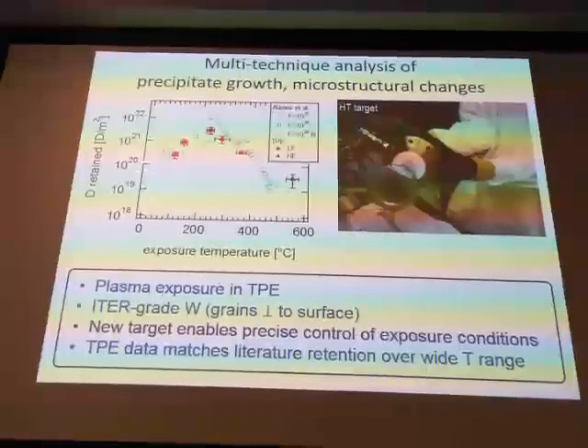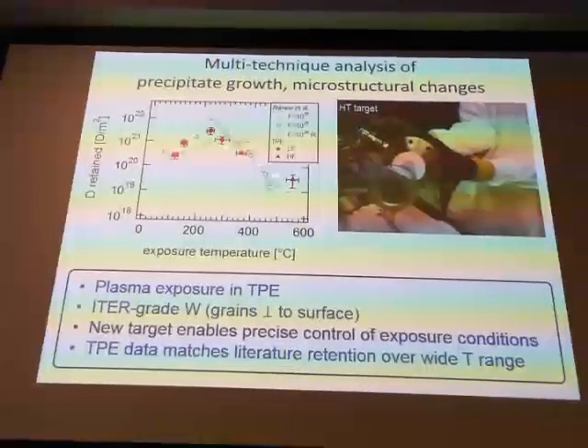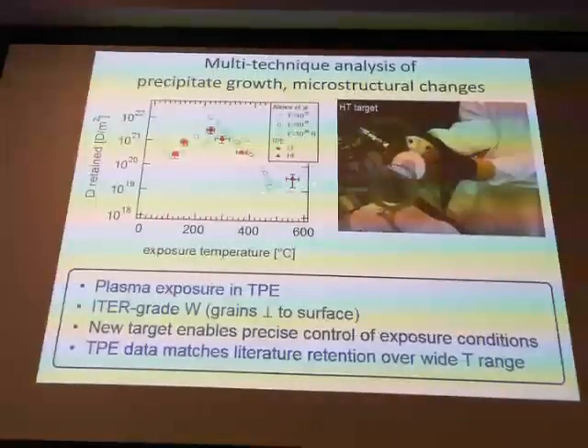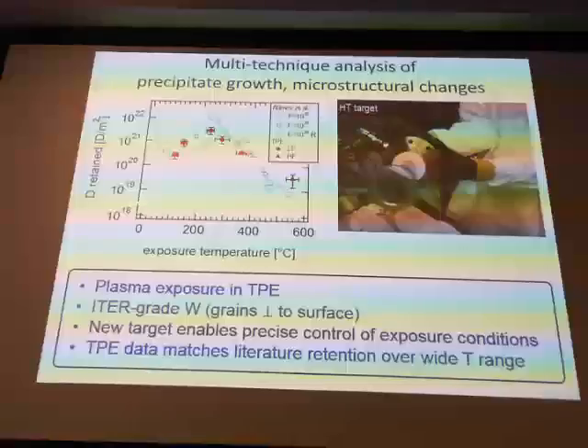This is an illustration of measurements that we had taken looking at retention in tungsten materials as a function of exposure temperature. And you can see that the general behavior here is that it starts out relatively low at low temperatures, and then at intermediate temperatures around 200 C or so, it increases and reaches a peak and then diminishes thereafter, and at high temperatures is just above our detection limit here, which is about mid 10 to the 18 deuterium per meter squared or so.